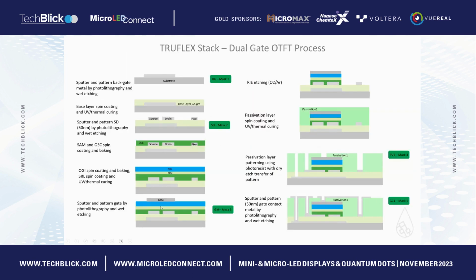This just shows the process flow. It's using photolithography, masking and patterning, wet etching, dry etching, coating, UV curing, and other types of fairly standard processes that you would find in an amorphous silicon backplane. So we use a dual gate device. So it has 2 gates, a bottom gate and a top gate, mainly for exclusion of light from the transistor to stop it from changing its properties when under high illumination.